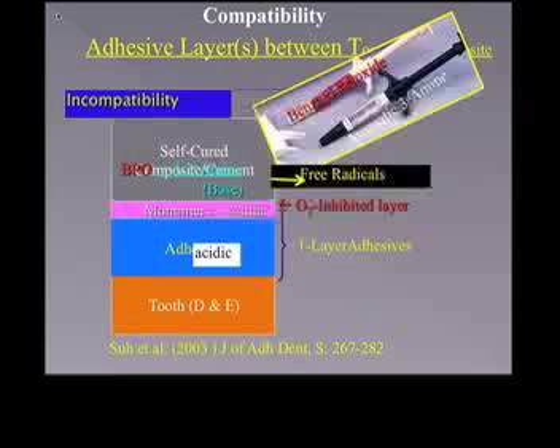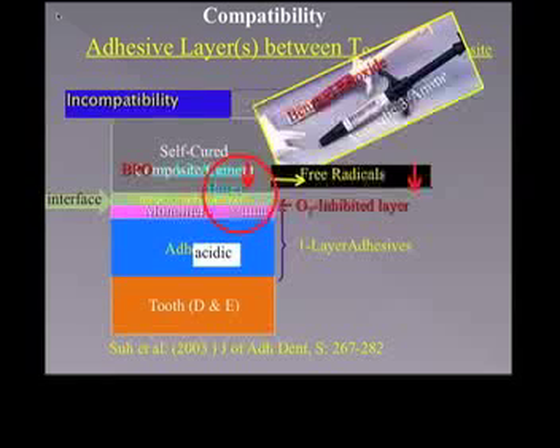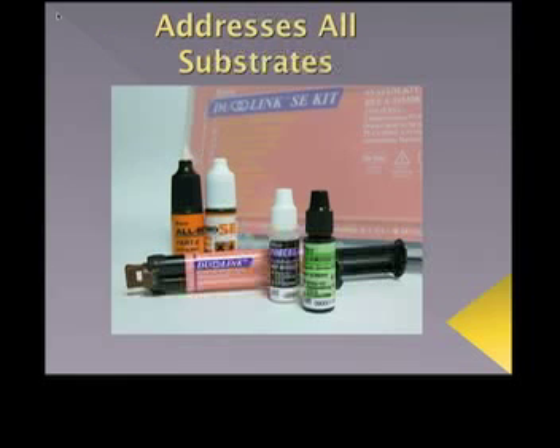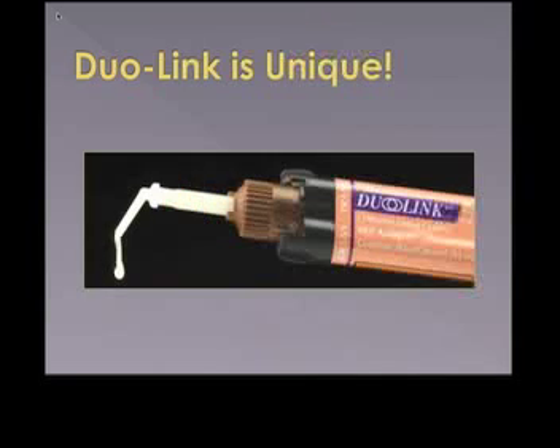Again, BISCO has packaged a quality dual cure adhesive system that provides evidence-based adhesive direction to the clinician, depending upon individual indirect substrate needs, whatever you're bonding to, whether it be non-retentive, retentive, zirconia, lithium disilicates. This is really incredibly unique, in a number of different ways. Again, it has a 5-minute self-cure mode intraorally, allowing for easy and quick cleanup without interfering with bond formation.